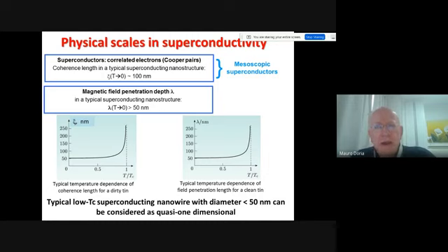And if the mean free path is smaller than the diameter, then the electron has collisions in the orthogonal direction. I'm worried mostly about the orthogonal direction, and the physics should change dramatically. The mean free path usually can be obtained because if you multiply the resistivity by it, it gives a constant number: rho times L gives a constant number. So I would like to understand, because I think that there is another crossover set by the mean free path. Usually these materials have a mean free path of 50 nanometers or 10 nanometers, and that should change the behavior if you have a wire with a diameter of 100 nanometers or 10 nanometers. Don't you think so?